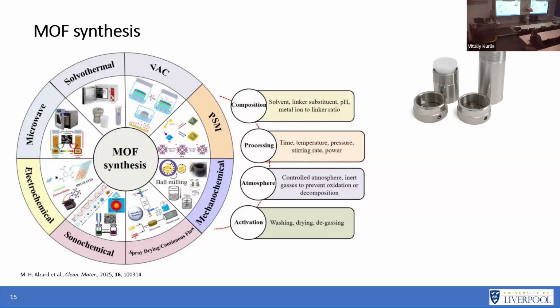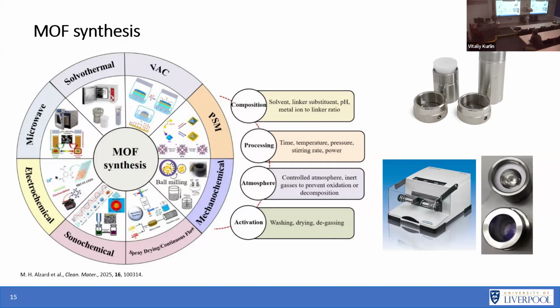Solvothermal synthesis is typically done in a solvothermal jar, such as the one here. Basically you put this in an oven, seal it up, and then under pressure, you will hopefully form some nice, pretty crystals. You can also do mechanosynthesis, which is my favorite. You put everything into a jar with a very small amount of liquid and shake it at really high frequency. You basically beat it up for like 30 minutes or something, and then you end up with a nice powder at the end. It's a really efficient way of synthesizing materials. If you work on materials, I would try synthesizing many of them mechanically, because you might just find that it actually works.